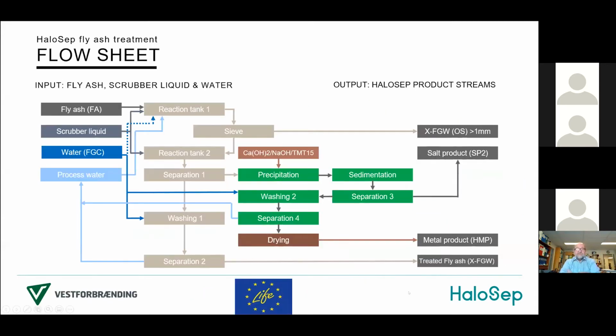A little bit into the green box. What is the actual flow sheet? This is a simplified flow sheet, but it tells you a little bit what's going on. On your left, you see the fly ash, the scrubber liquid, and the water source. It's going into reaction tank number one. From reaction tank number one, the material is sieved, and we take out oversized treated material, the gray box on the upper right. Going from the sieve into reaction tank number two, and from reaction tank number two into a separation stage one, where we separate the treated material, the treated fly ash, from salts and metals in solution. The treated fly ash then goes into washing stage one, where we allow it to be washed with water.